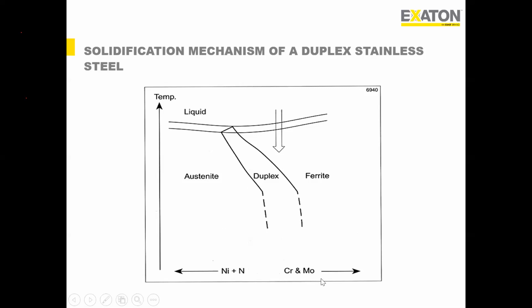fight each other. These ferrite stabilizers try to pull the liquid weld metal to room temperature in a ferritic structure. On the other hand, these two alloy elements, nickel and nitrogen, the austenite stabilizers, try to pull it into the austenitic phase. And with this balance, the final structure gets solidified in between, and we get a duplex structure. This is one. The second very important factor is the cooling rate.